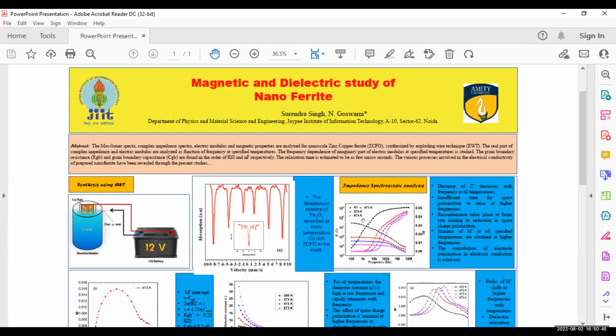Then we studied the magnetic properties, and here in the magnetic case we can see that at lower temperature magnetization has improved, and it is following the hysteresis loop also. And the second one is after doping. It is found that the magnetic nature in one case, the magnetic hysteresis loop, is more dominant, and all these properties of our material encourage us toward the application of ferrite bead.